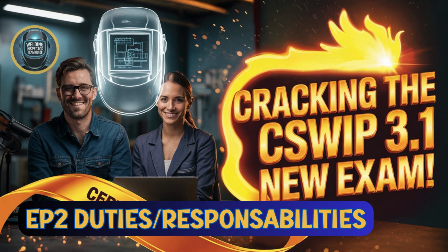The whole job really boils down to that. Observe everything relevant that affects weld quality, from the very start to the very end. Record the inspection findings, especially any problems, and compare everything observed and recorded against the requirements, the standards, codes, drawings. Observe, record, compare. That really sums it up.